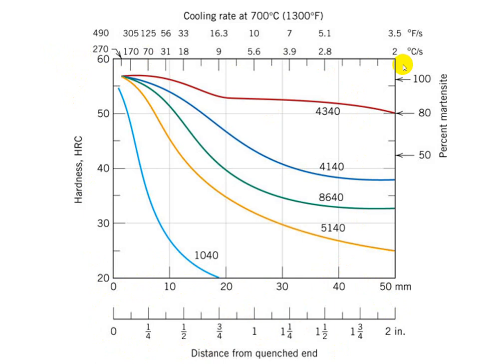So again you have the millimeters, these are the distances from the Jominy head per millimeter per inch, and on the other side you have the cooling rate in two different units. And here we have the hardness. For example, all these alloys they have same carbon content, different alloying elements. Obviously we have different carbon equivalent. So among all of them, 4340 is the most hardenable, 4140 next, and so on.